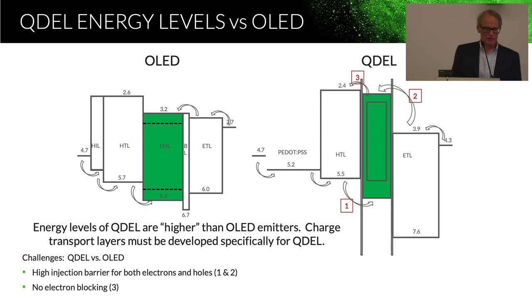Take a look at the energy levels. This is for a cadmium-free quantum dot electroluminescent device. This is all we work on at Nanosys. One thing you see is that the energy levels are a little shallower, closer to vacuum, than the analogous OLED. The other thing you can see is that it's not a very great structure. In fact, there are fairly large hole and electron injection barriers, and it looks like there's the potential for electrons to spill over from the emissive layer into the hole transport layer directly, which would obviously lead to inefficiencies in the device. Part of the reason for this is that people are using the same charge transport materials that people have used for other purposes like OLED. Nobody's yet building dedicated materials for cadmium-free quantum dots, and that actually needs to happen.